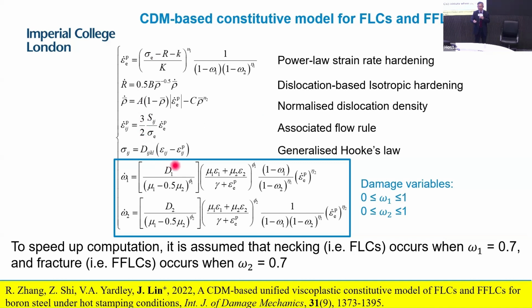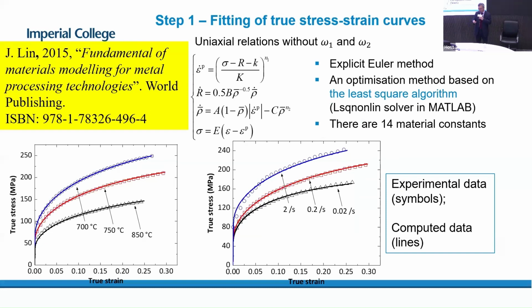This is a general viscoplastic constitutive equation, which probably most people know because they come from engineering, I believe. And we introduced two damage parameters, omega-1 and omega-2. One controls the diffuse necking behavior of materials, and the other controls the fracture of materials. We put this into two steps. The first step is the uniaxial relationships. We generate proper data from the uniaxial tensile test, and then fit the experimental data to determine the parameters like K, N1, B and so on in the constitutive equations. The method is given in my book, Fundamentals of Materials Modeling for Metal Processing Technologies, if some people have read it, I believe.